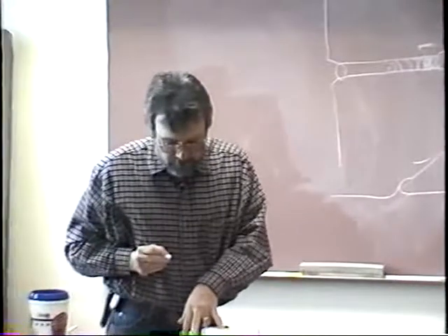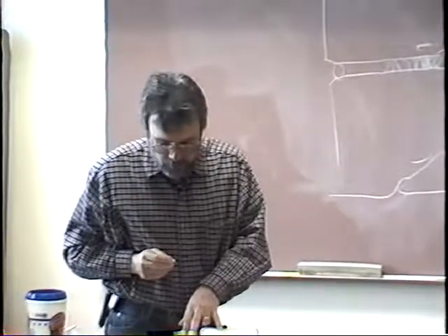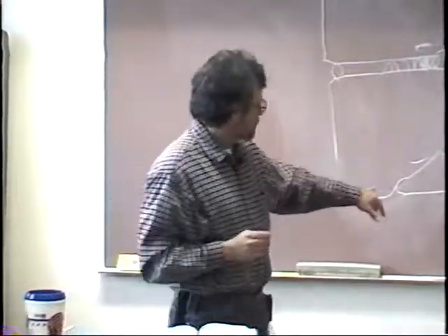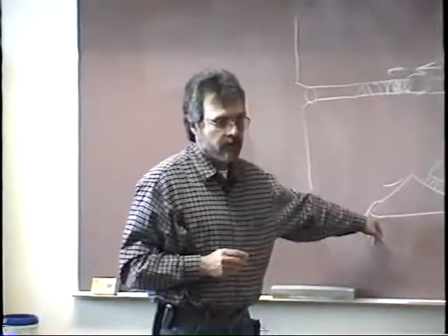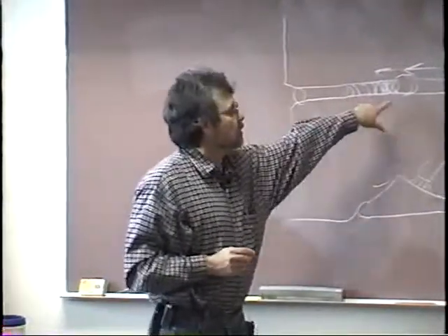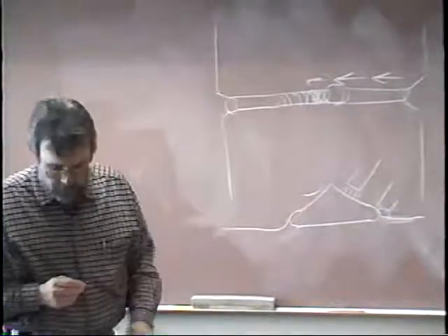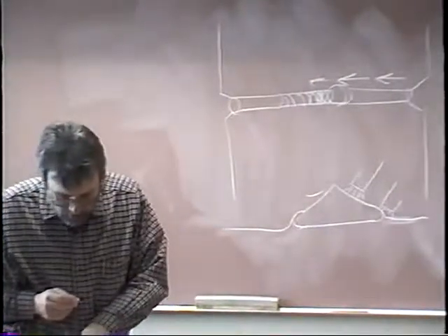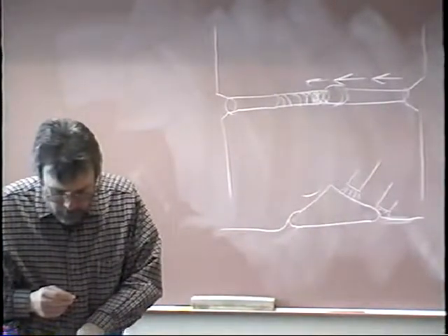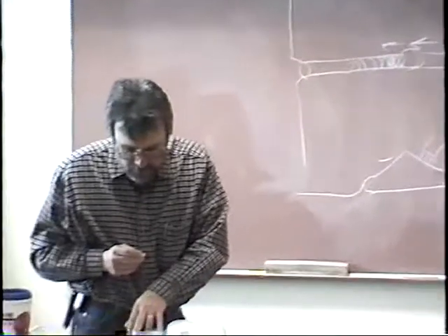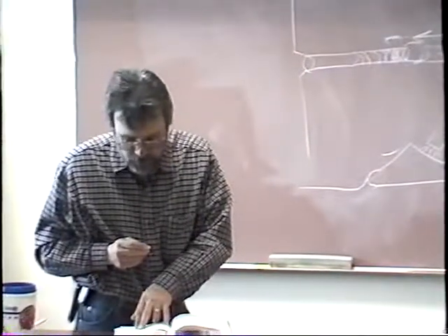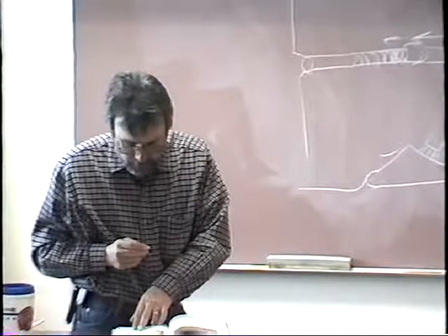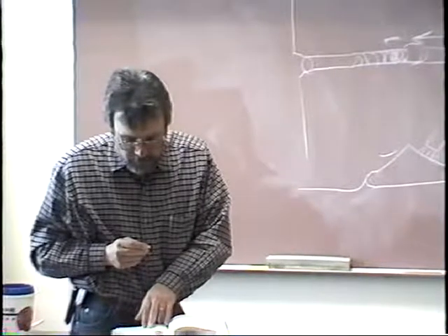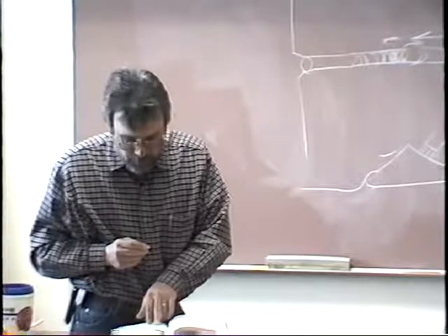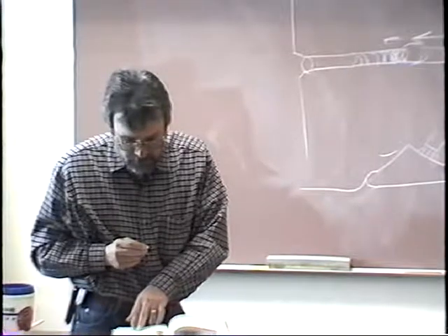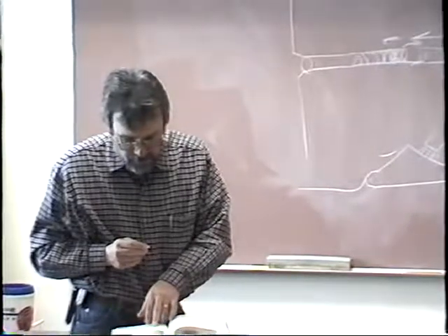All right. Next paragraph here reads, the procedure for welding toward the heavy end of a bead is very similar. This is what he's referring to as the heavy end of the bead. The end of the bead without a keyhole in it. This allows time for the heavy end of the weld to get hot enough to obtain good fusion with the oncoming molten metal. As soon as the bead that is being deposited gets close enough, the whipping motion should be directed toward the heavy end of the bead to which the tie-in is being made.